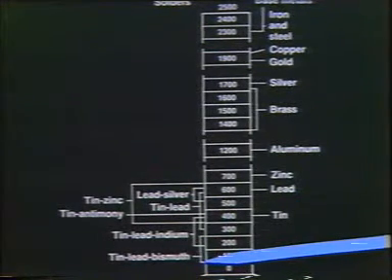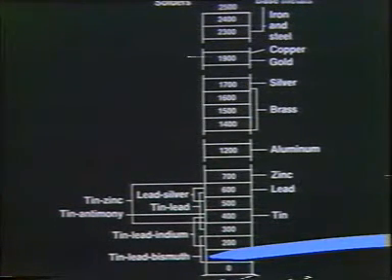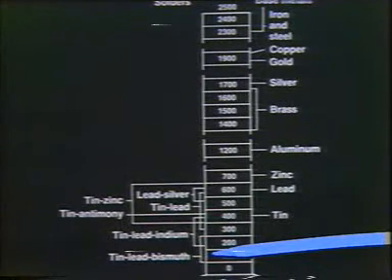You'd say, well, they have no use there. It's too low melting, and I never want to use that as a solder. But the fact of the matter is, indium is one of the most beautiful materials to solder with you can find. It wets just about everything, and in fact, it wets glass. And so if you wanted to solder a piece of glass to a piece of metal, the thing that you would use would be indium. And in fact, it's used for a lot of glass seals in electronic devices. You use indium as a seal in the glass.